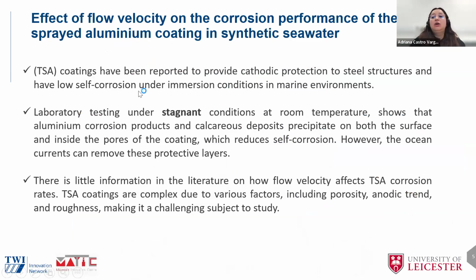So first of all, what we note basically is that these coatings have been reported to provide cathodic protection to the steel and have low self-corrosion. Laboratory tests and also field tests demonstrate that they perform very well. After some time of exposure, we found aluminum corrosion products and calcareous deposits, and they precipitate on the surface, but also inside the pores of the coating, which is beneficial because it reduces the self-corrosion of the coating. However, in real life, ocean currents can remove these protective layers. Unfortunately, it's not clear how they affect the removal of these protective layers. There is little information in the literature on how the flow affects it.